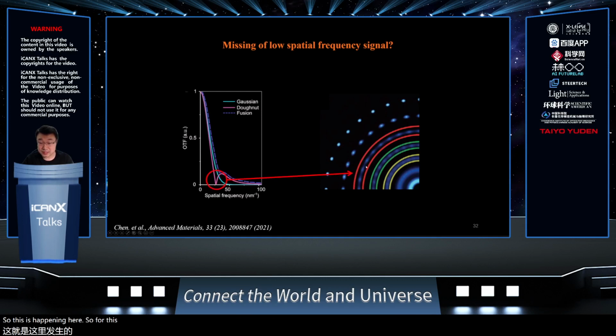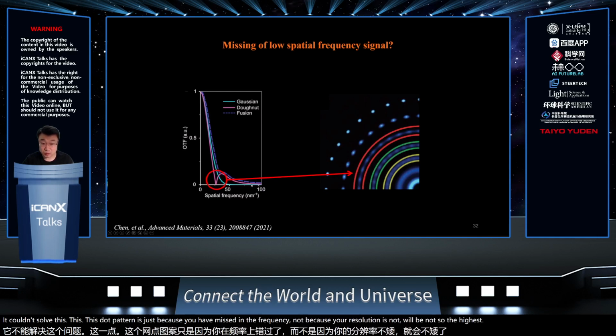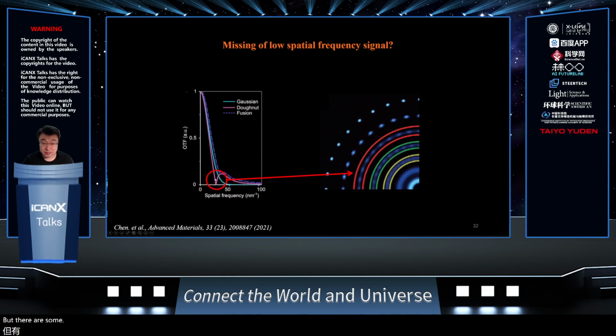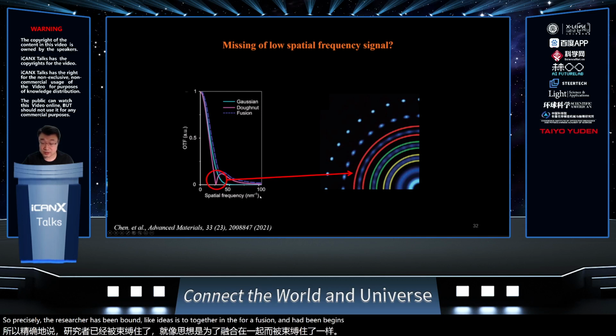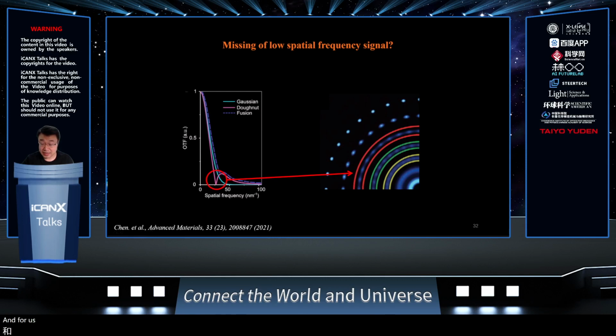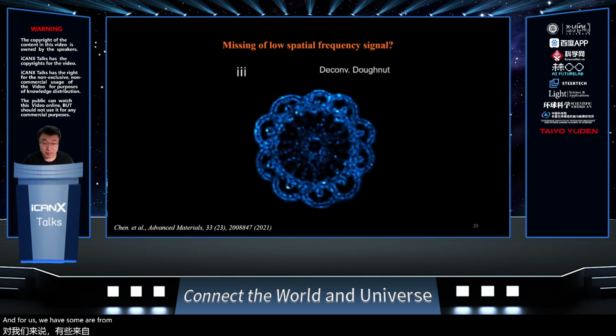For this spacing, given our resolution it should be really clear, but you see that it couldn't resolve this dot pattern. It's just because you are missing the frequency, not because your resolution is not good enough. The highest resolution is really high, but there's some missing frequency. The Gaussian beam is actually good with this lower frequency. Previously, researchers added these two together in the Fourier domain, and then they could solve this problem. And for us, we have an even better way of doing that.